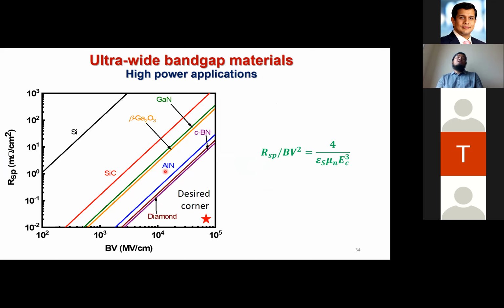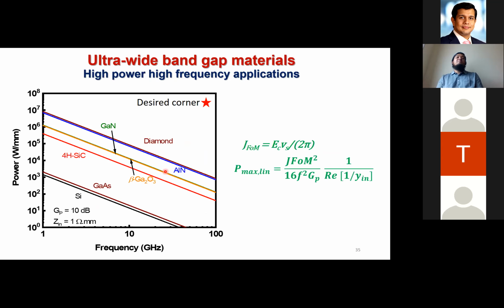But these materials are new. There are a lot of materials related challenges that need to be solved before they can come into application. As I mentioned, the substrate is one of the major economic bottlenecks for commercialization. These days, the diamond and aluminum nitride substrates are really small, so there will be another new round of challenges with those. Looking at high frequency, high power applications with Johnson's figure of merit and the maximum linear power, we see that introducing materials like diamond and aluminum nitride can enable a new range of applications beyond the capability of gallium nitride or silicon carbide. Everyone is pretty excited about these new materials, and there are a lot of efforts going on around the world.